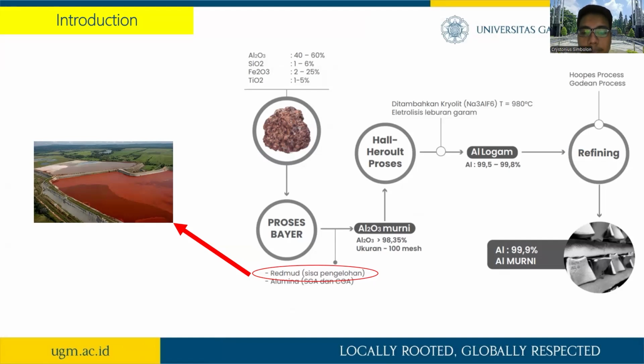Based on data from the Indonesian Central Bureau of Statistics, processing bauxite through the Bayer process produces approximately 0.8 until 2.5 tons of red mud waste for every ton of alumina obtained. Indonesia certainly has a bauxite processing industry in West Kalimantan and it will continue to be built.